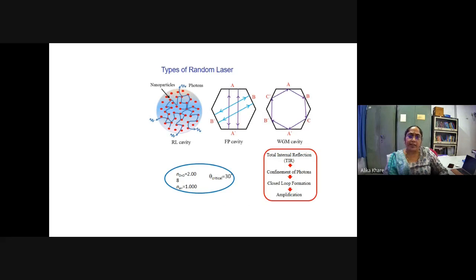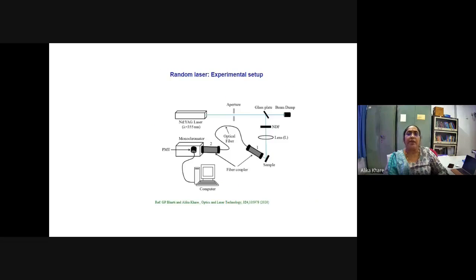So we have our ZnO film, and we demonstrated the lasing action in it. Since the ZnO band gap falls around 360 to 380 nanometers, and its emission is around 380 to 390 nanometers, we used the excitation source at lambda equal to 355 nanometers, which is the third harmonic of the Nd:YAG laser.